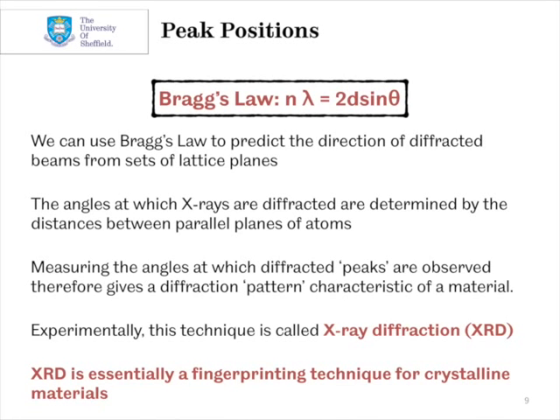So you can see that the angle is determined by the distance between parallel planes of atoms. So if we measure the angles at which the diffracted peaks are observed, we get a diffraction pattern that's very characteristic of a material. And experimentally, this is the basis of x-ray diffraction.